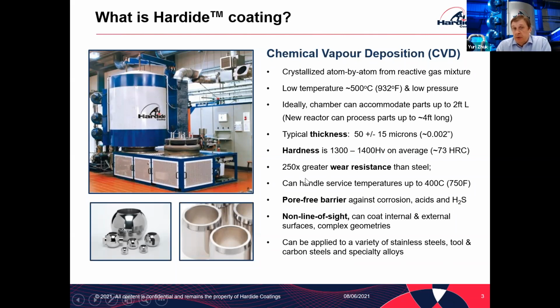The main reason why it's used by the customers is wear resistance. Just to give you an idea, it is about 250 times more wear resistant compared to steel. The coating can be used up to 400 centigrade. It is a virtually pore-free coating, which can be a very good barrier against corrosion, against some aggressive chemicals such as acids, and it's also quite an effective barrier against H2S. So sour oil, sour gas can be very good areas for the use of our coating.